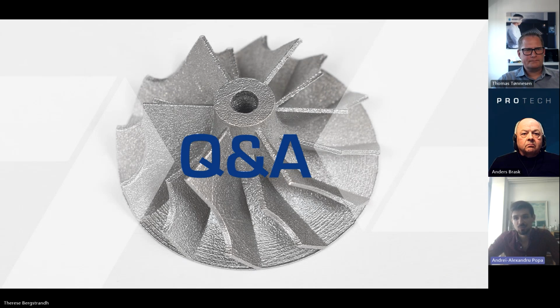So yeah, the short answer is that you can use AI to process it, but it's not really AI. It's more of a quick algorithm that can quickly see what parameters are good, but you still need to perform tests. You still need to characterize them for density, for strength, for continuity. You can have a very dense part that has one crack through the middle. It's still a useless part, right? Or you can have a part which is rather porous, but has the pores very well distributed, which is maybe better. I hope that answers the question to a certain extent.